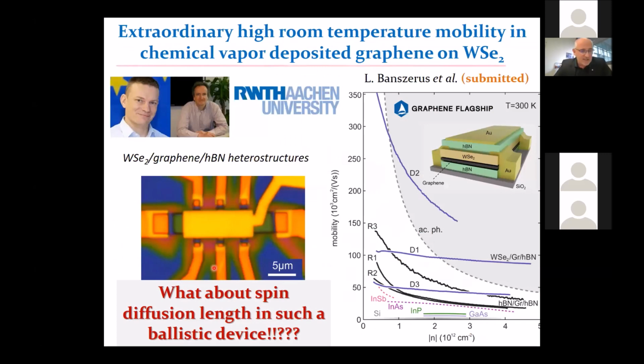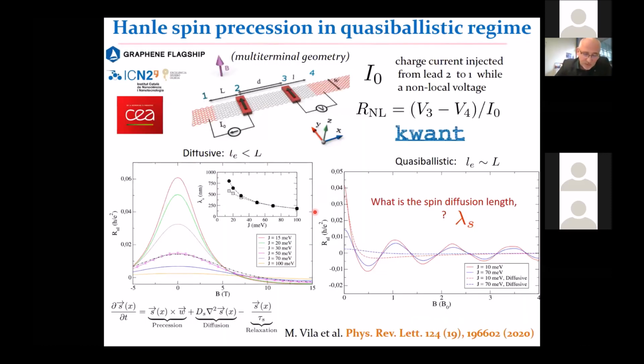Very recently, there is still a debate about the explanation, but our colleagues at Aachen University succeeded in encapsulating graphene not only with boron nitride, but also with a strong spin orbit coupling material, tungsten diselenide, and they found an unprecedented mobility, reaching values never seen before, even larger than what the acoustic phonon limit would predict theoretically. So here we have something very interesting, still under analysis. But one clear question is, what about the spin characteristics in a device where electrons flow in a ballistic fashion throughout the device? This is something that we had to analyze, especially from the simulation point of view.